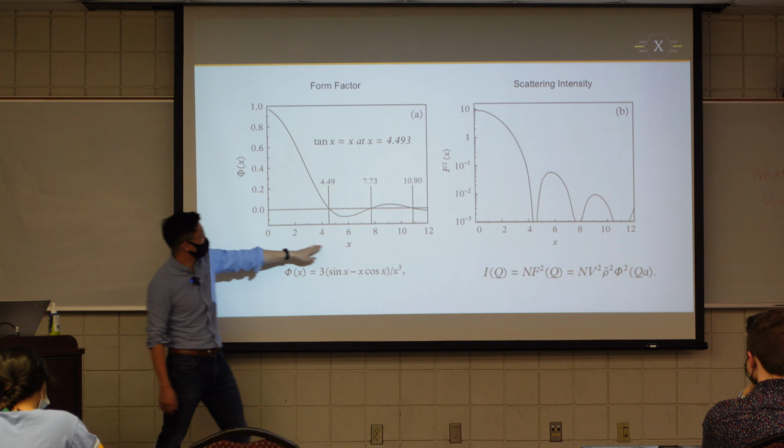It can go as high as, let's say, 20 inverse nanometers. So what would be the size scale we are looking at if it's 20 inverse nanometers? Even higher. Keep going, 20 inverse nanometers will be somewhere here. But what's the real space? Roughly 3 angstroms. Okay? So that's what I showed everybody at the beginning of the lecture: X-ray can see any features from a few angstroms all the way to a few hundred nanometers.